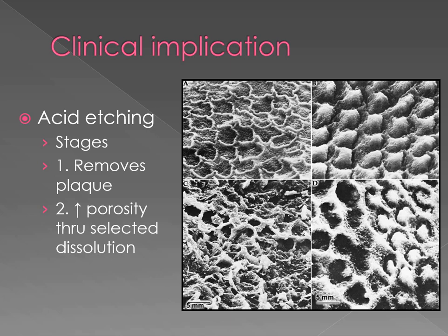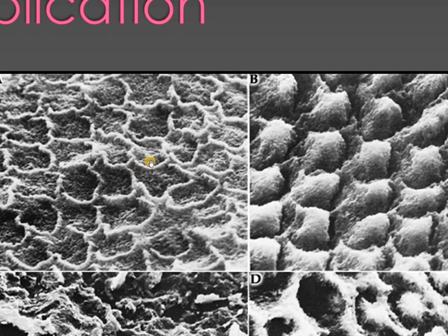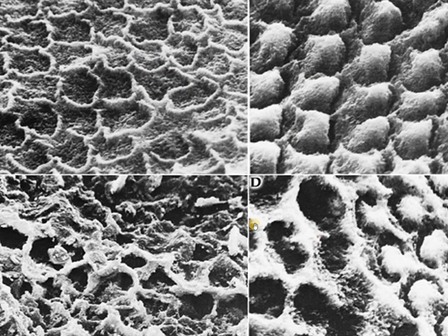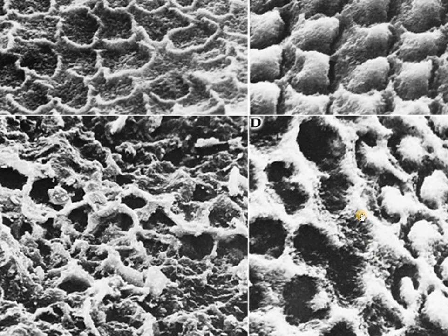In the process of restoration of the teeth, there are times when we will have to stick something to the surface of the enamel. When you put a layer of acid on top of enamel, you will appreciate that the enamel differentially dissolves. The rod sheath and the rod dissolve differentially in different conditions. In the first image here, the rods have disappeared and the rod sheaths are intact. In the second image, the rod sheaths have disappeared and the rods are intact. In the third image, it is haphazardly dissolved. And in the fourth image, you can see both types A and B.